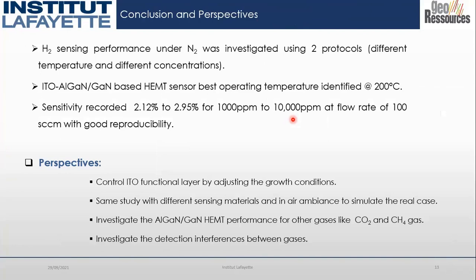So the ITO-based sensor's performance has been analyzed with two experiments. First, by varying the temperature, and second, by varying the concentration of H2. The best operating temperature was found to be 200 degrees from experiment 1, and the ITO-based H2 HEMT sensor is capable of detecting a wide range of concentrations with a high sensitivity of 2.95% for 10,000 ppm of hydrogen from the second experiment.